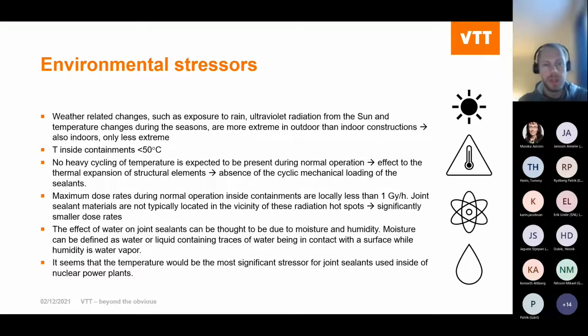The effect of water in joint sealants is due to moisture and humidity. Moisture is basically water which is in contact with the joint sealant surface, and humidity is related to the water vapor pressure in air. And it seems that temperature would also in this case be the most significant stressor that the joint sealants are facing inside nuclear power plants.